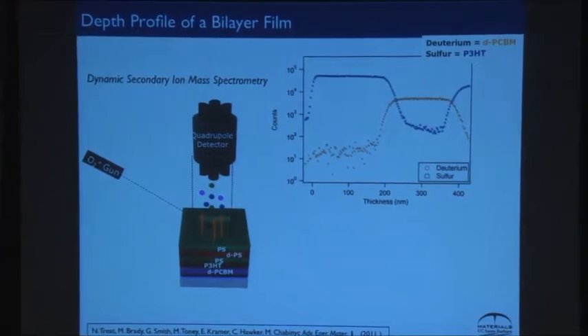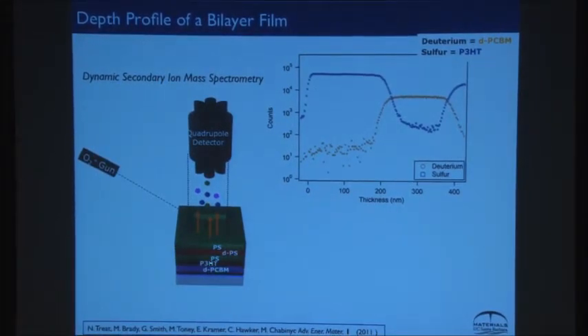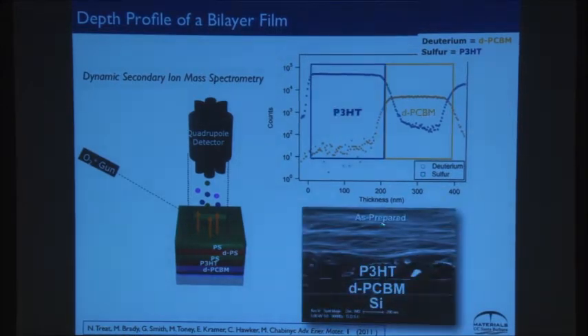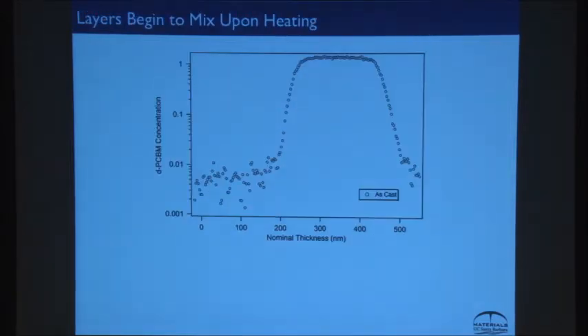What you see then is we'll just look at the deuterium signal from this and the sulfur signal from that, just to give you a sense of that. And what you find is in this bilayer, as prepared, you see both phases. You see the PCBM layer at the bottom. You see the P3HT at the top. Now what happens? Let's heat this up. So you start heating it up.